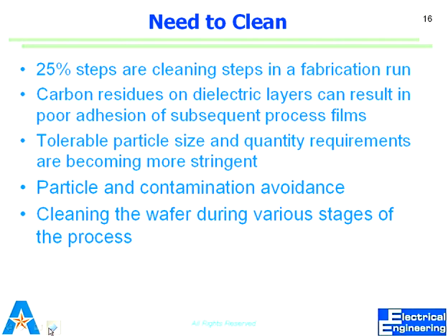We might have done some reaction with an alkaline solution and you want to neutralize it. What are alkaline solutions? pH greater than 7, basic solutions. KOH is potassium hydroxide. Potassium is considered a metal and can degrade the device if it seeps into the substrate. So before any high temperature process, I want to neutralize any potassium on the substrate. Cleaning is not always just cleaning; you have to neutralize chemicals that might have come in contact with the substrate. It can be carbon left over from polymer from earlier reactions, particles, films, or oil. So we need to clean after almost every major process.